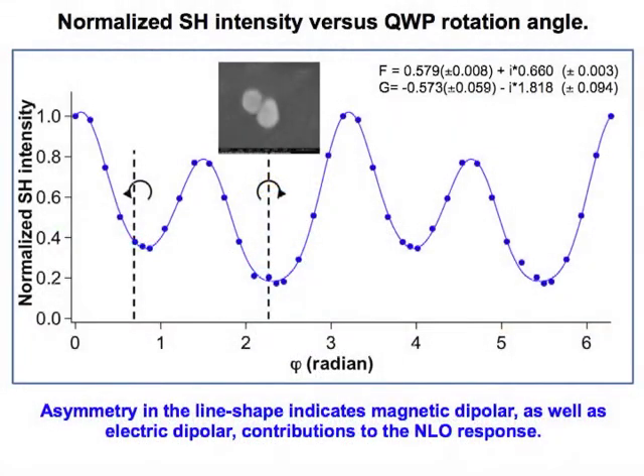SHG data obtained as a function of the fundamental polarization state can be analyzed to quantify relative contributions from electric and magnetic dipoles. Here, F represents the electric dipole component, while G quantifies the magnetic dipole. These results clearly demonstrate that plasmonic nanoparticles can be used not only for electric field amplification, but also as a magnetic field transducer to amplify magnetic fields upon optical excitation.